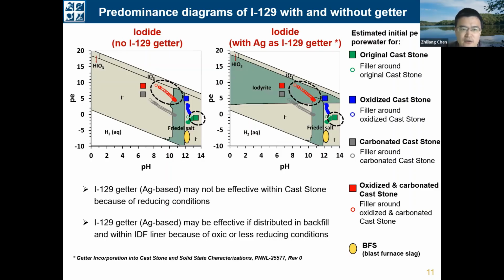Firstly, the redox state for the original Cast Stone, as you can see, indicated by this green square dot, are in the region of highly soluble iodine for both 2 systems. So that means the redox state of the original Cast Stone is unfavorable for iodine stabilization, even for the system with the getter added. So the getter may not be effective within Cast Stone because of the reducing conditions there.